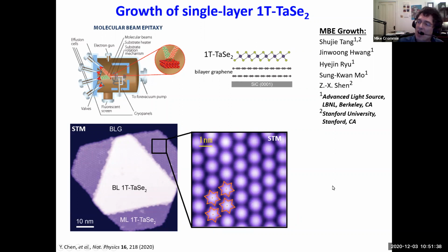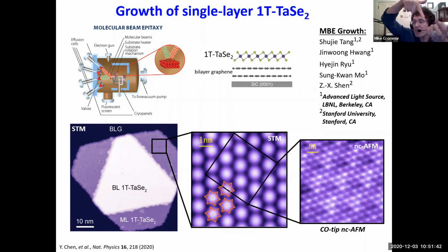With STM, it's hard to see the atoms, but if you want to see the atoms, what you do is you put a carbon monoxide molecule on your tip and you perform non-contact AFM, and that's what we did. And when you do that, you can see the atoms just fine. So here they are. These are the atoms that we measure with a CO, carbon monoxide tip, non-contact AFM. And these are the selenium atoms, and they're pretty much where you expect them to be. So it all kind of looks kosher and good.